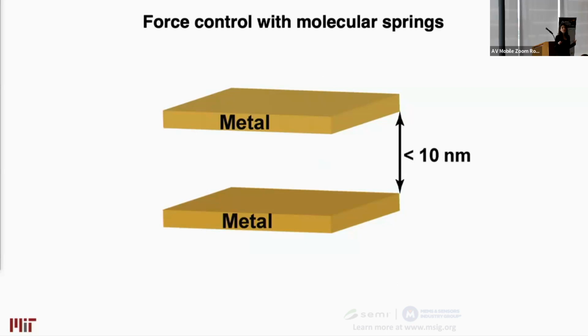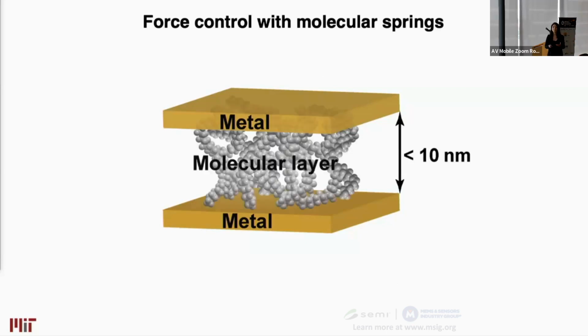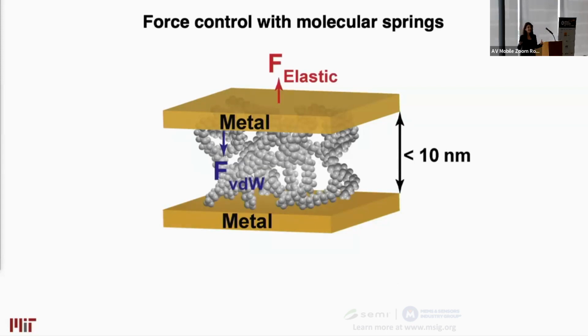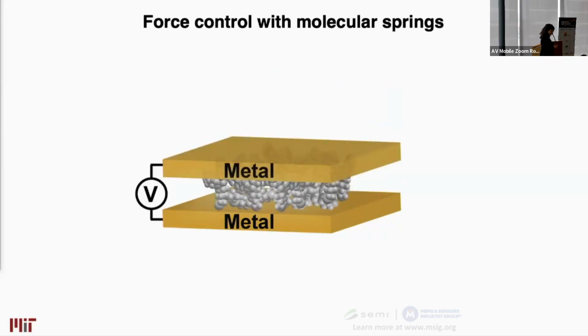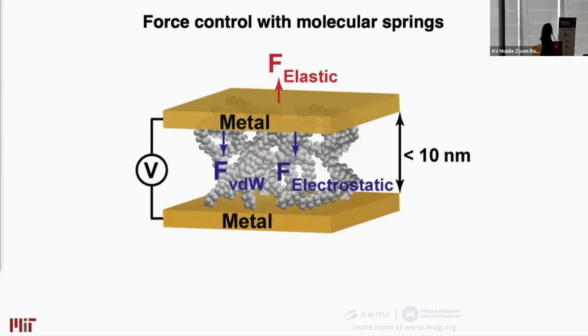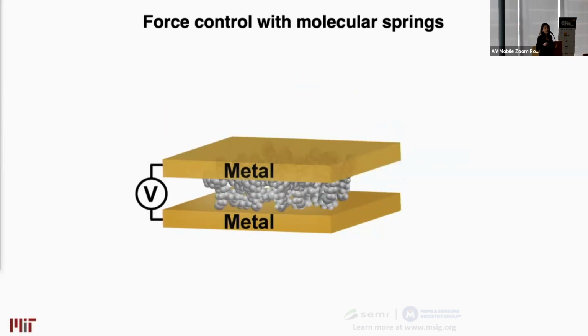So imagine instead of a switching gap that's made out of air or vacuum, we now have molecular springs in the gap. So the molecules, depending on their mechanics, can provide an elastic restoring force to balance out the surface adhesive forces. That first helps us fabricate structures that are much smaller than what conventional fabrication techniques would allow us to fabricate reproducibly and reliably. So in this particular example, sub 10 nanometer gaps. At the same time, if you actuate your device, the elastic force in the molecules can help you modulate the surface interactions such that you can have this small device operate in a controlled and reproducible manner.